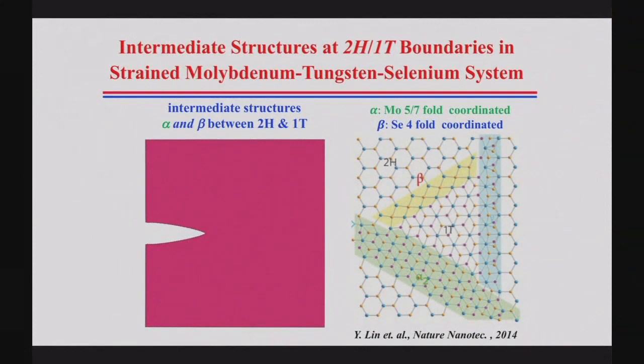And in the alpha structure, you have zigzag chains of molybdenum and sulfur, which is totally distinct from 2H and 1T. Whenever the material goes from 2H to 1T, you always have these intermediate structures, which have been seen by electron microscope. And we see the same structures when we do modeling. So this is again the crack propagation thing, and when we looked at the interfaces between 2H and 1T, we always found these alpha and beta structures.